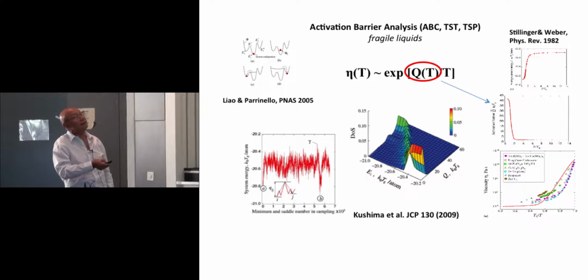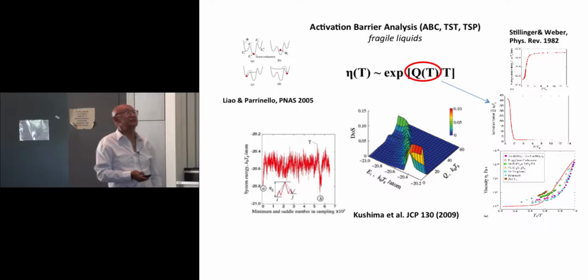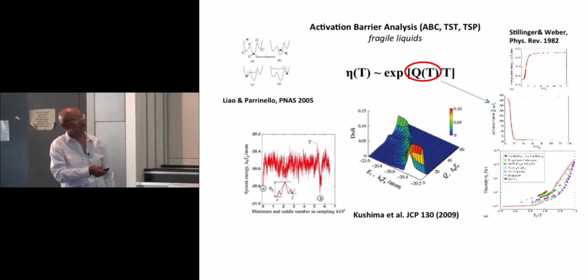But if you use this, you generate, this is one way to talk about the free energy, not the free energy, the potential energy landscape. You see a sequence, one particular sampling of a potential energy trajectory on the landscape, where you see a series of minima and saddles and so on. And so you can see that there are some low minima, like a basin from here. There's some high saddle point over here. But let me skip over the details and just say that if you use this method, which is no longer molecular dynamics, it's metadynamics, you can generate data of this kind.